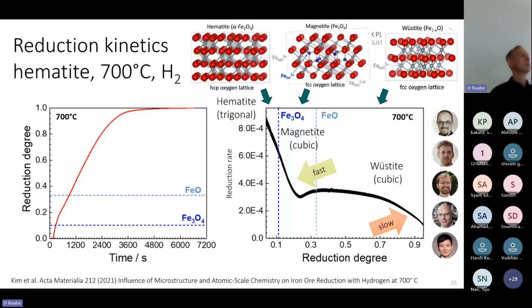So when we go a little bit deeper into the physics, we look at the reduction kinetics here for a direct reduction process that is taking place under pure hydrogen at 700 degrees centigrade. And that is, of course, by solid state direct reduction standards, a rather moderate temperature, but we do that on purpose to make things nicely observable. So when you take a look at the right-hand side diagram, then you can see that you plot here the reduction rate as a function of the reduction degree, as you see here.